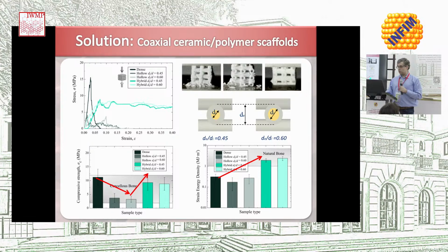What we also found is that you almost get no difference depending on the amount of polymer you get on the inside. So it doesn't matter too much if you have a very large channel with a lot of polymer or rather a smaller channel. So in principle, and because, as you can see on the plots, there is a slight decrease in the strength of the hollow structures when you increase the amount of channels.